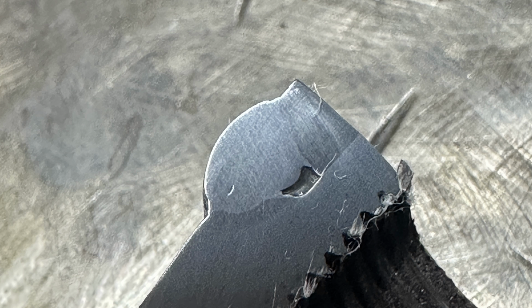Now, beyond that, there's a chunk of porosity that we see there for the first time, and that's very common because when you weld with super cold settings, anything that might be in it that would otherwise come out of the liquid molten metal will now be trapped because of how fast it solidifies. Now that crap you see in that complete lack of fusion at the bottom, that's actually just chemical etchant or naval jelly, so don't pay any attention to that.